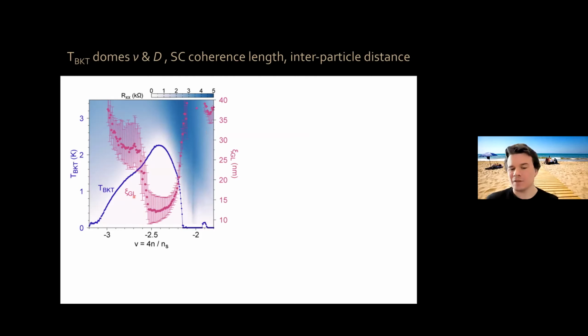As you can see, the superconducting coherence length in the system is extremely short. In fact, if I plot here the average interparticle distance for the system, this is this red trace. And as you can see, near optimal doping, the superconducting coherence length is bounded by the average interparticle distance. I should remind you that these moiré quantum systems, the superconductors, are the lowest charge density superconductors that exist in the world by far, by orders of magnitude, because of the large moiré unit cell lattice.